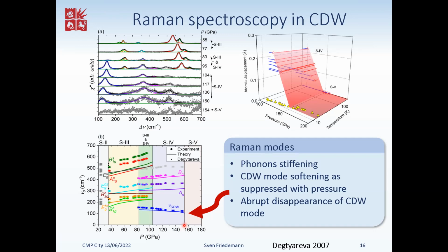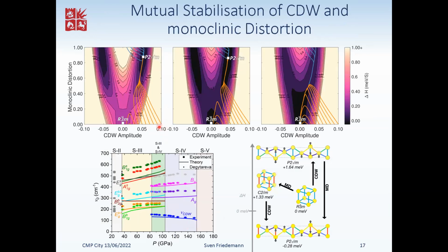And we can understand this by looking at the energetics of the two things that happen. Namely, if we start with the rhombohedral structure that's present in the sulfur 5 phase, so outside the charge density wave, you can do two things to it. You can either introduce the charge density wave, we approximate it with a 3/4 modulation, or you can introduce the monoclinic distortion, but each of them individually gives you a state that's higher in energy. So none of them individually is actually favorable. Only when you combine the monoclinic distortion and the 3/4 modulation, you get something which is lower in energy. So that tells us that they mutually stabilize each other.